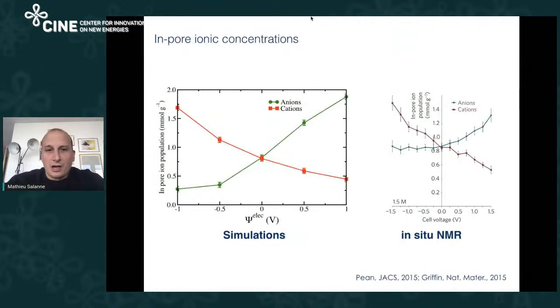So then you can also compare with more complex experiments. Here you have a comparison between simulation on the left and nuclear magnetic resonance on the right. It's not exactly the same system, but the comparison is fair, I think. And you see that when you switch from 0 volt, which is a middle point in each case, and at 0 volt, you have as many anions as cations inside the pores. And when you start to apply a positive or negative voltage, you see that you separate them. You start to enrich your electrode either with cations or with anions. And you see that the numbers are very similar between the simulation and the experiments. So again, I think that at least we have a good qualitative representation, if not totally quantitative.